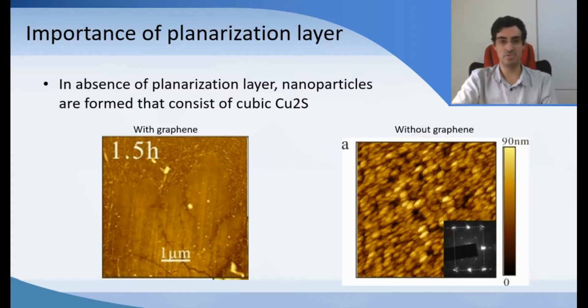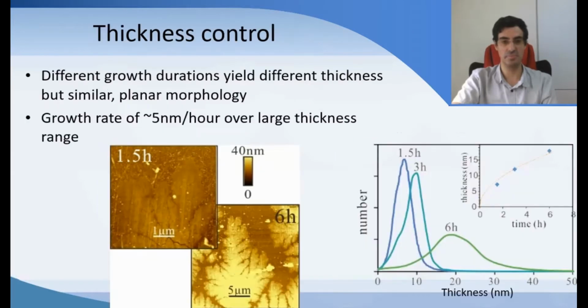If we're growing for longer times, we only see that the flakes are getting bigger and thicker. We're not seeing that the roughness decreases or increases if we're going thinner, as you would expect for 3D materials. So it is a layered material, and it's growing layer by layer, but it can be grown thicker. This is very different from 2D materials, which normally just grow a single layer. And then once the either catalytic surface or the epitaxial attachment is completed, they will self-limit. They will not grow a second layer.